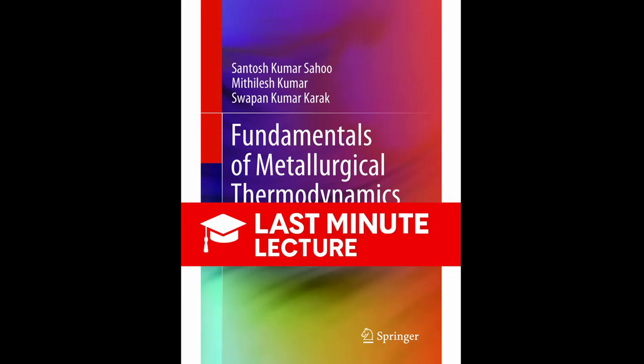Finally, in this part, section 4.9 introduces the Clausius-Clapeyron equation. This equation is indispensable for predicting or controlling phase transitions. It is absolutely vital for managing things like the boiling point of metals under vacuum or how pressure might affect the melting point of a casting alloy. The derivation relies on the fundamental equilibrium condition. During a phase transition, say from phase 1 to phase 2, the Gibbs free energy of both phases must be equal. G1 equals G2. So if you change the temperature and pressure a tiny bit, the new equilibrium state requires dG1 to equal dG2.